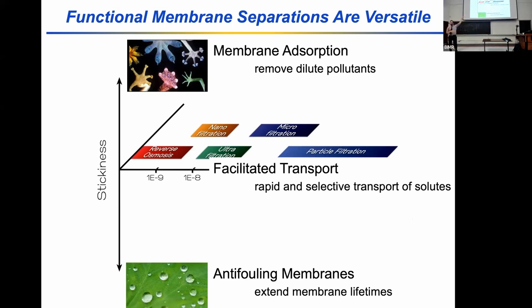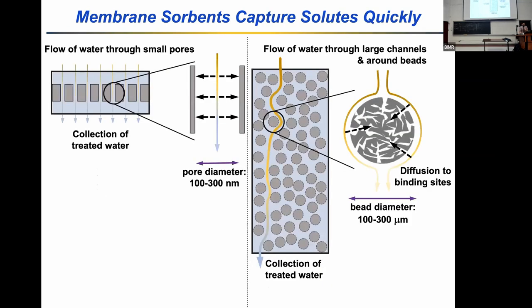If I had a really sticky membrane, you could imagine making membrane adsorbers like Professor Ghosh does, and they're able to selectively capture molecules from solution with high affinity. Well, on the other end, as Abhishek and Matthew were showing me, they've got some really nasty water, and the contaminants in that water will stick to the membrane surface as it operates. And so maybe you could create some anti-fouling surfaces that would resist the adhesion of these nasty bits as your membrane process was operating. And so this is why we're trying to modulate the pore wall chemistry.